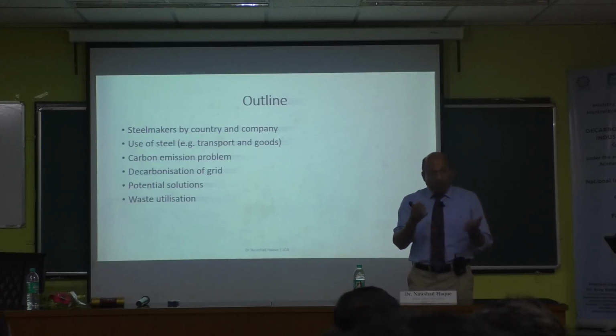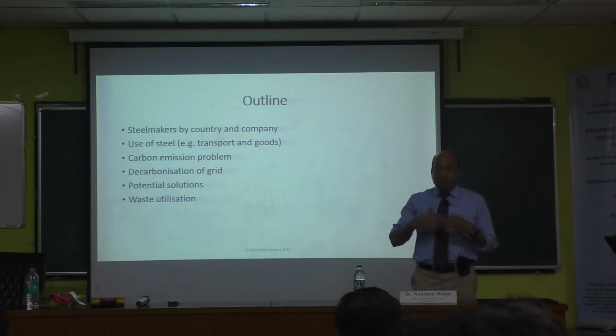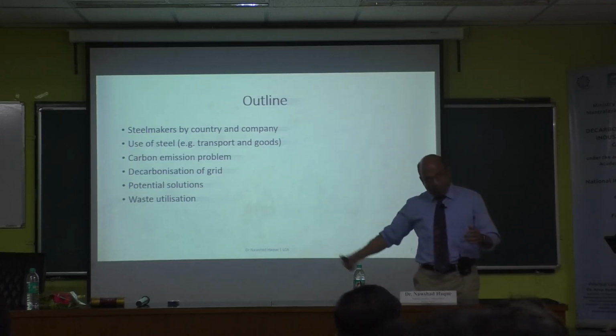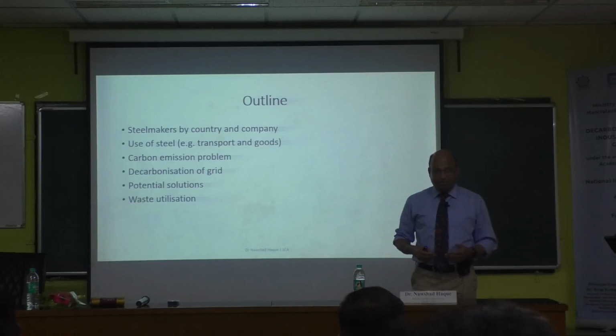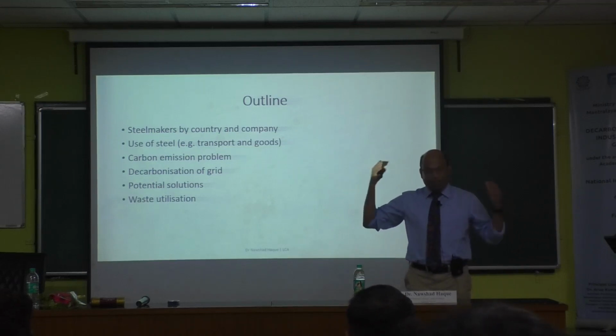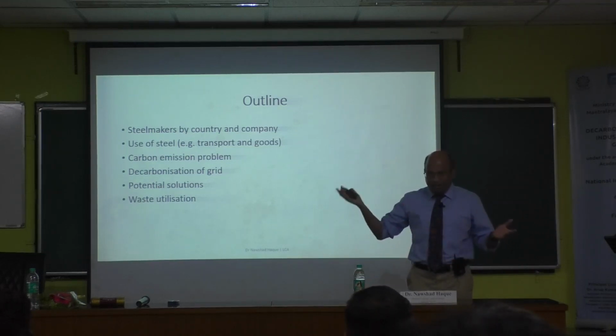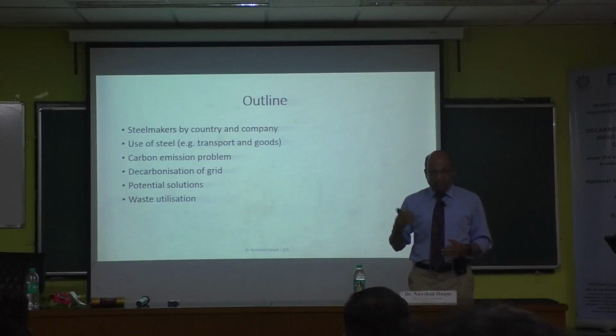So even the global average is 10, as I said, because global electricity is mixed. So it's 700 million, something like that. So overall, one is the specific footprint, another is the overall footprint because of the total production in the world. So if you want to reduce the CO2 footprint of metal, where should you focus then? Steel. Even though the concentration is low, the magnitude of steel is so high that it kind of dwarfs the other metals. So these are the things.